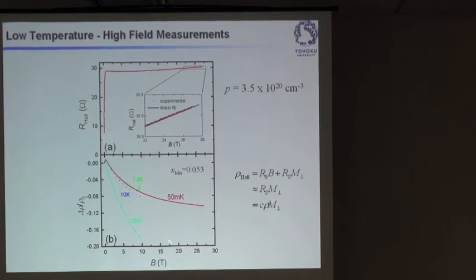And at this high magnetic field with low temperature, we can saturate this term here. Magnetization is saturated at low temperature and high field. And also this anomalous Hall coefficient, which has a resistivity component in it, can also be saturated at low temperature and high magnetic field. Then the remaining slope can be measured, because this part becomes constant. And the remaining part, which is the ordinary Hall effect, is shown here.